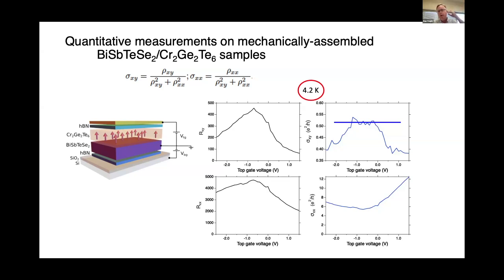But that's also what's seen in the magnetically doped topological insulators that exhibit the parity anomalous state. And that's because you don't have zero conductivity. There are some geometrical factors that are in, and if there's any current inhomogeneities, those will also affect things a little bit. But we're seeing a full value of the 1/2 e squared over h within what we expect to be the experimental uncertainties.